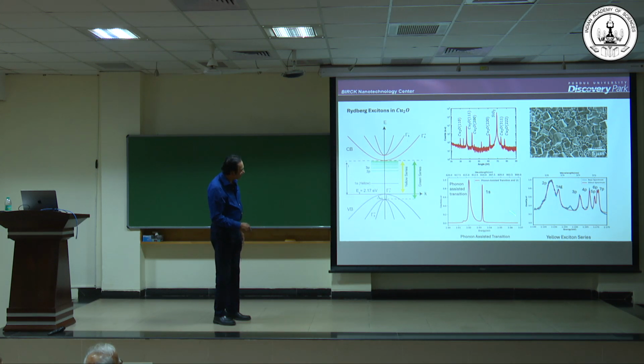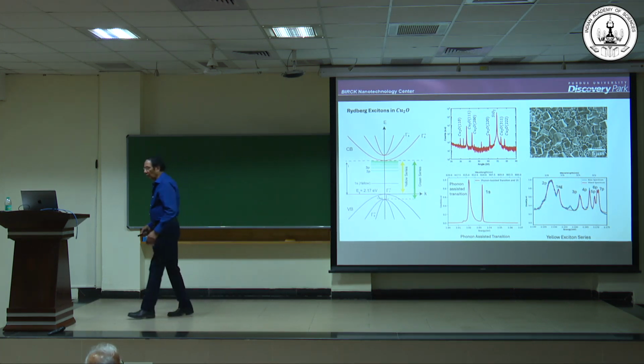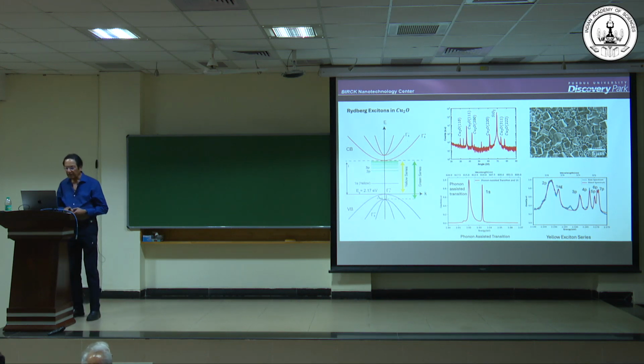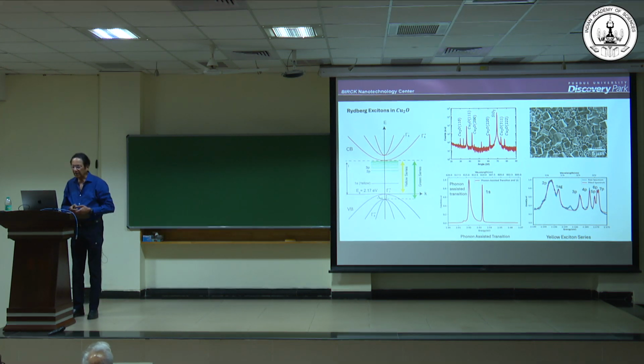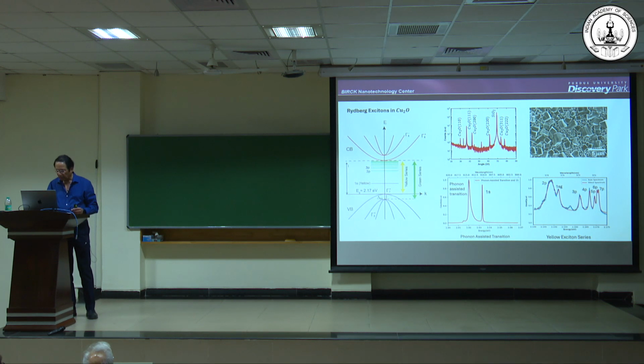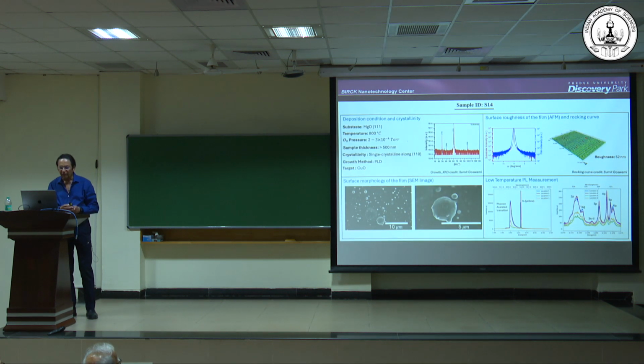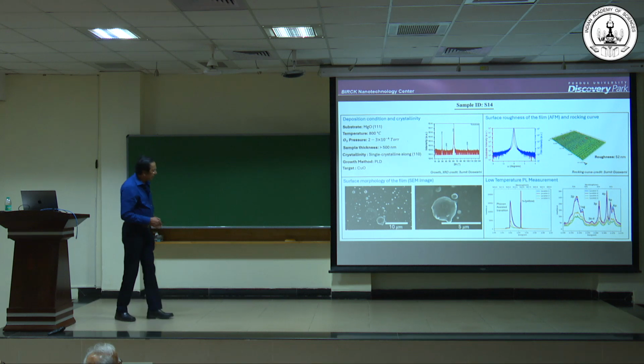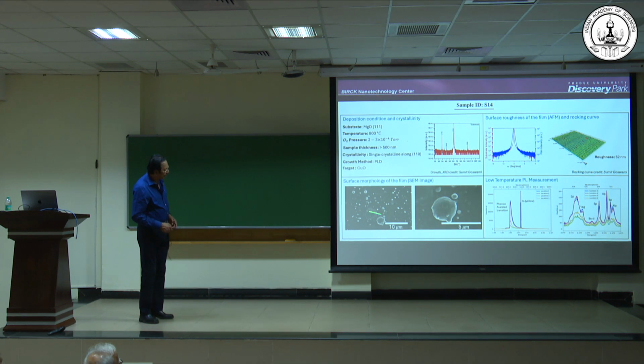So you can see the Rydberg states. They can see this 1s exciton. This is a phonon assisted transition, and then you can see the first Rydberg states, 2p, 3p, 4p. They can really see all these Rydberg states, right? Only problem is this is essentially copper converted into copper oxide, cuprous oxide, and it's not a viable way. So now we're making PLD films of these. Ignore these particles. This we know how to get rid of. But now these are films, actually background films.